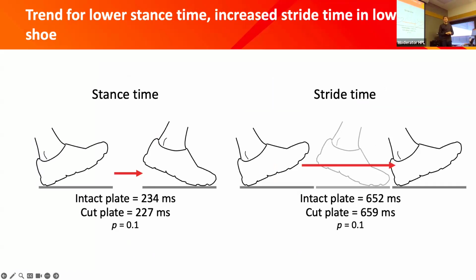We also looked at some of the spatiotemporal differences between these two just to see if that was a factor as well. And we did see some significant change, or a trend for significant changes here. So intact plate versus cut plate stance time decreased slightly from 234 milliseconds down to 227 milliseconds. P-value was 0.1. And the stride time consequently increased to reflect that. So the intact plate was about 652, and that went up to 659. So there are slight spatiotemporal changes actually happening.